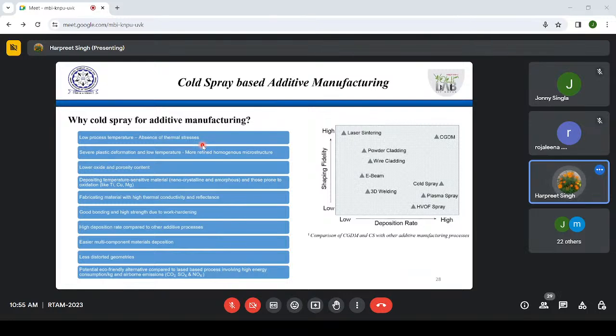So you might have understood the defects in additive manufacturing processed parts by now, that there is the presence of thermal stresses owing to the high temperatures involved in lasers and so on. With severe plastic deformation and low temperature, more refined, homogeneous microstructures can be obtained here. As I already showed you, here we get severe plastic deformation happening, which leads to grain refinement. And once grain refinement is there, you can get much better properties, right?